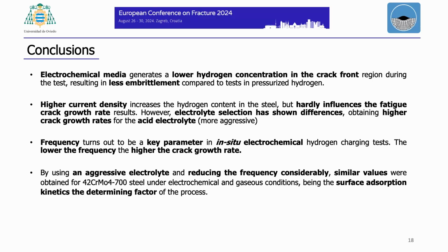And by using an aggressive electrolyte and reducing the frequency considerably, similar values were obtained for the 42CrMo4 steel under electrochemical and gaseous conditions, the surface adsorption kinetics being the determining factor of the process.